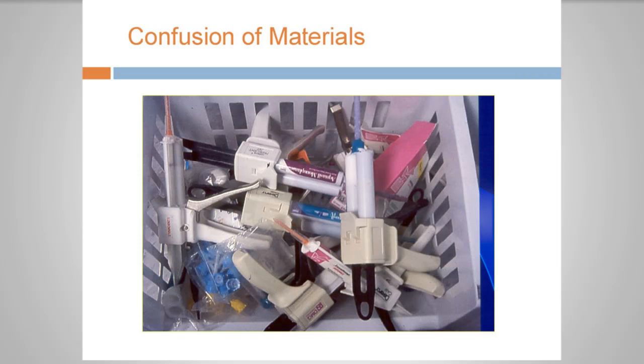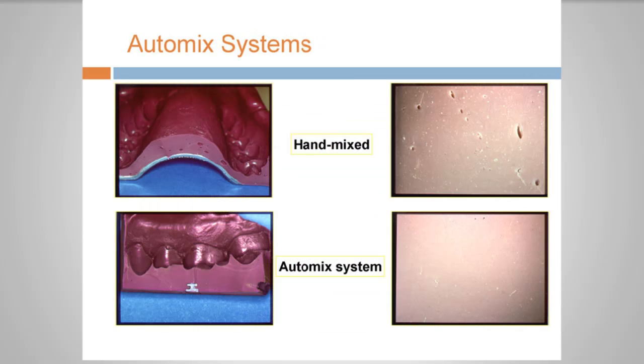And with the auto mix system versus the old hand mix, it's made a huge difference on the outcome of the material, because when you were hand mixing it, you would incorporate a lot of the air bubbles, and with the auto mix systems we eliminate a lot of the air bubbles, and the air bubble was never here, it was always on the margin up in here. That was where the problem was. But these auto mix systems are very consistent. It's a consistent amount of mix, base and catalyst, setting time, which definitely cuts it down.